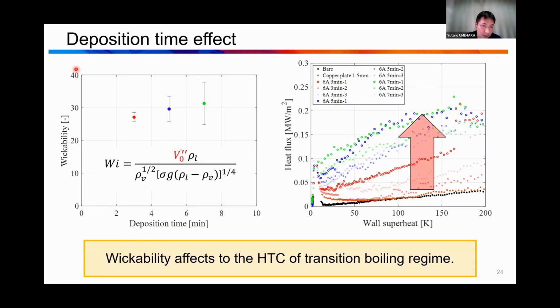So this is the result, wickability versus deposition time. When we increase the deposition time, the wickability also increases a little bit. So this may have some effect on improving the high heat flux and high heat transfer coefficient during the high wall superheat range after the quenching.